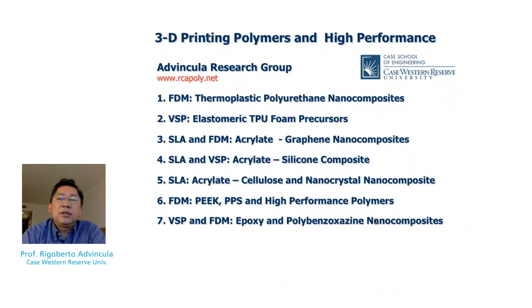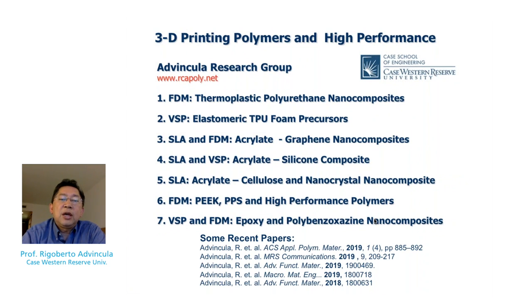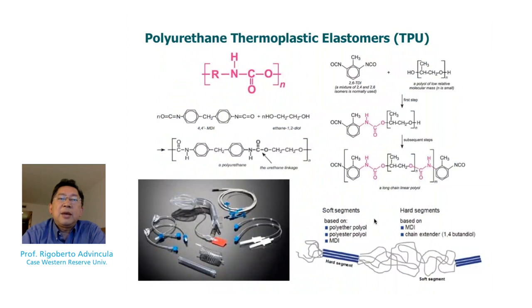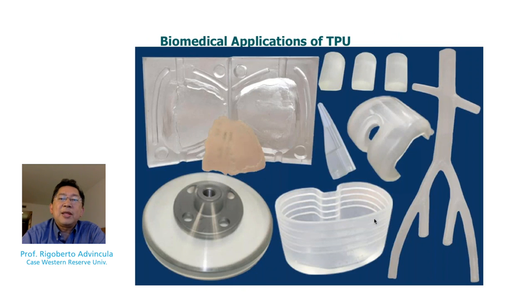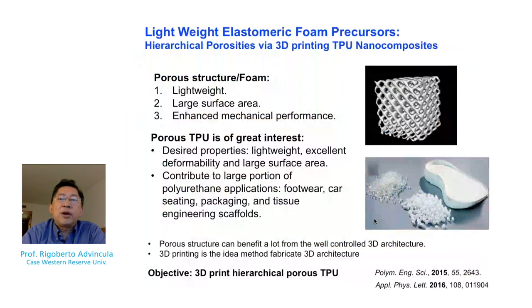Our group has a lot of focus these days on 3D printing of polymer nanocomposite materials, including thermoplastics, thermoplastic elastomers, thermoset elastomers, and thermosets. And some of our recent publications are listed here. Let me just demonstrate one or two material systems. One is this polyurethane thermoplastic elastomer that we published 2 years ago. The thermoplastic TPU material owes its properties because of the hard and soft segments afforded by the isocyanate and polyol components. And in fact, there's a lot of interest for this in biomedical application and I dare to say, of course, wearable electronics.